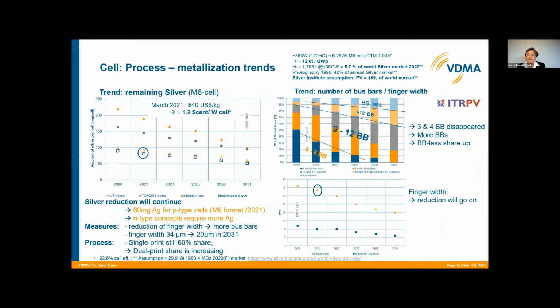So how can we decrease the price of the products? One big part is of course the silver price. And we see here that for the M6 format, we have at the moment about 80 milligrams of silver necessary per cell, and this will decrease to 50 milligrams. But the N-type concepts, like TOPCon as well as heterojunction, need much more silver. So the reduction needs to be done, and will be done by reducing the finger width and using more bus bars. As you can see, the finger width will decrease down to 20 microns. And the print process will also help to reduce the silver amount in the future.